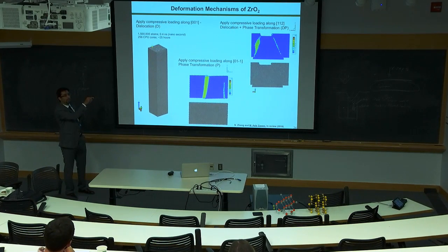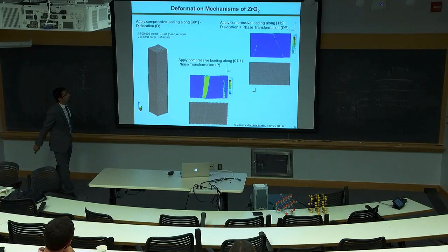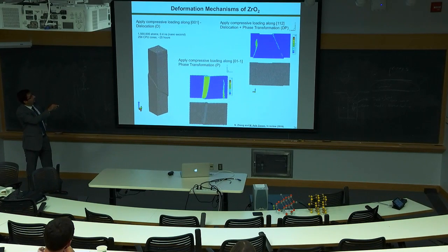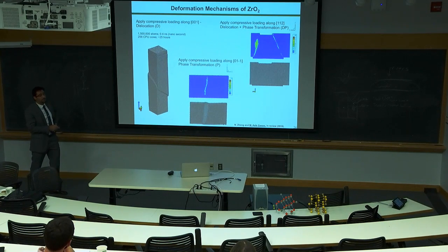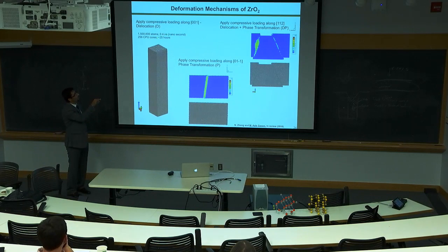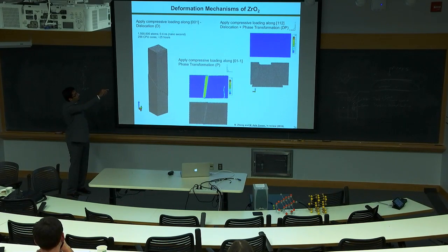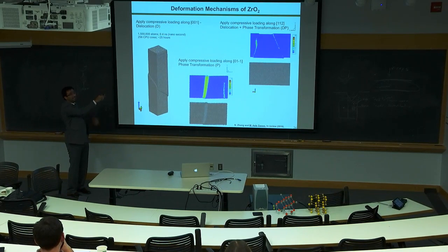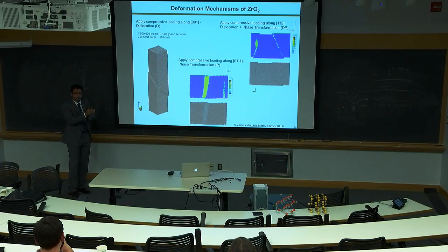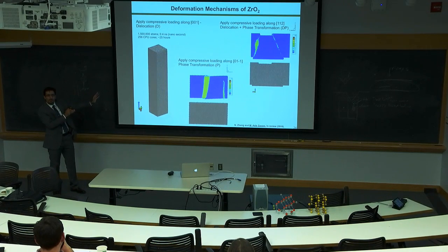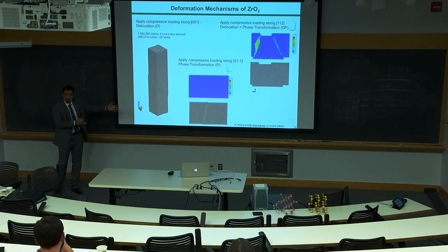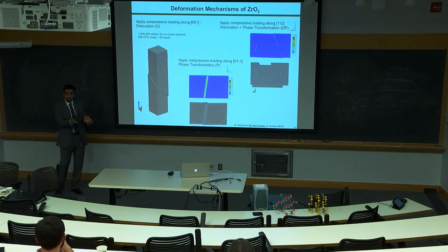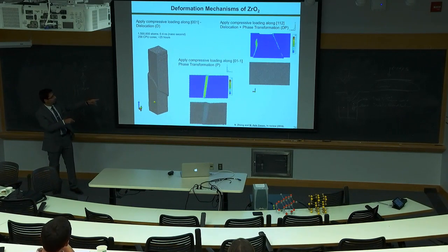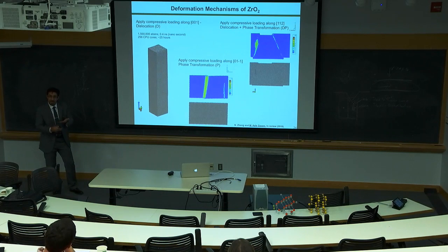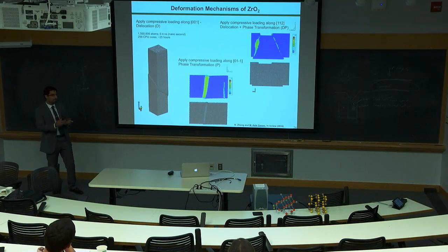What do you need actually to simulate more than 1.5 million atoms? Basically, you need 256 CPU cores for 25 hours. But again, the total simulation time is 0.4 nanoseconds. So we need to transfer this to a phase field model. A phase field model can run for seconds of simulation time. These can give us some mechanism information about the deformation mechanism and failure mechanism.